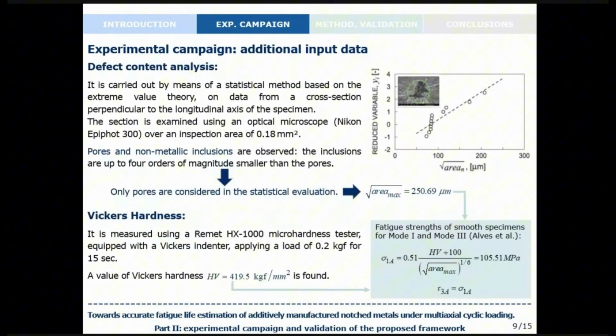And then a defect content analysis is carried out by means of a statistical method based on the well-known extreme value theory. We perform this analysis on the data from a cross-section perpendicular to the longitudinal axis of the specimen. And here we notice that both pores and non-metallic inclusions are present, but since the inclusions are up to 4 orders of magnitude smaller than the pores, only the pores are considered in the statistical evaluation. And thus, we obtained a value of the square root of the maximum defect size equal to about 250 microns.